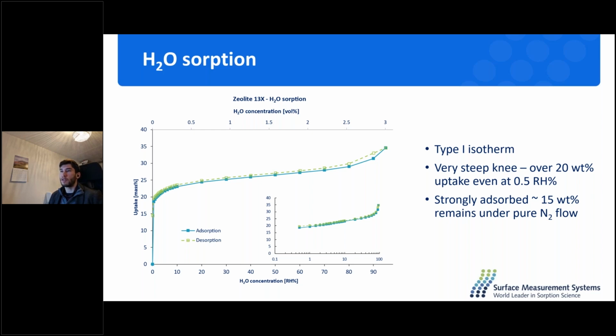So if we look at the desorption branch, what we see is that under a pure nitrogen flow, it's nearly impossible to regenerate it. What happens is there's nearly 15% of water still trapped in the material, no matter how long you wait. So it's clear that there are strong interactions towards water.